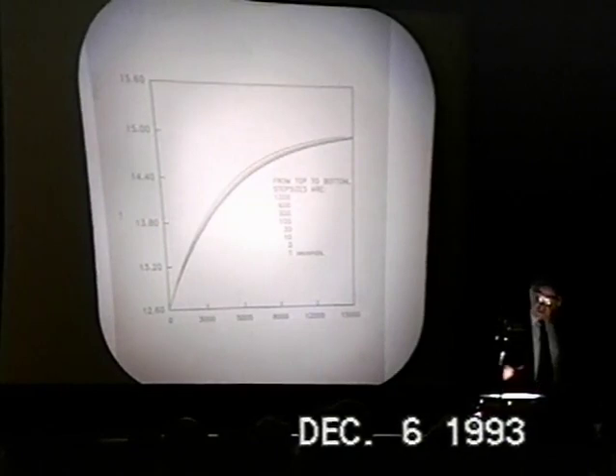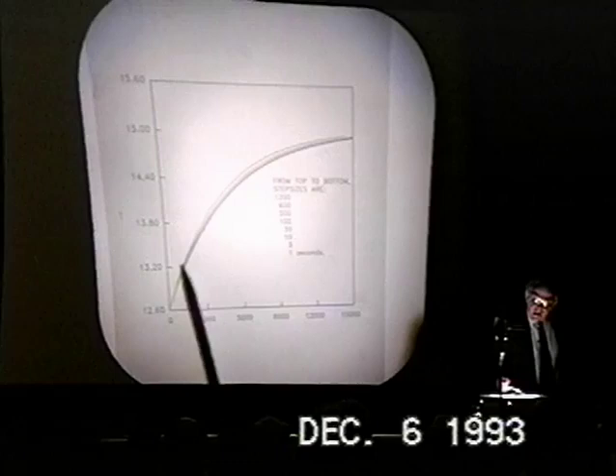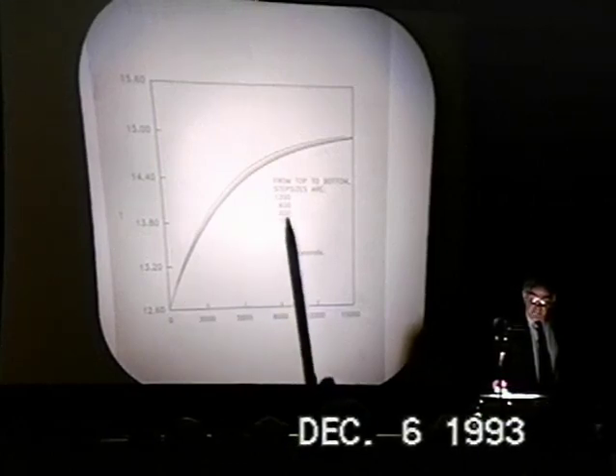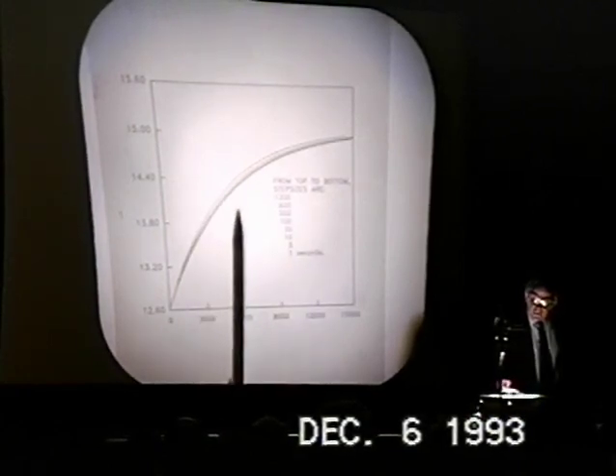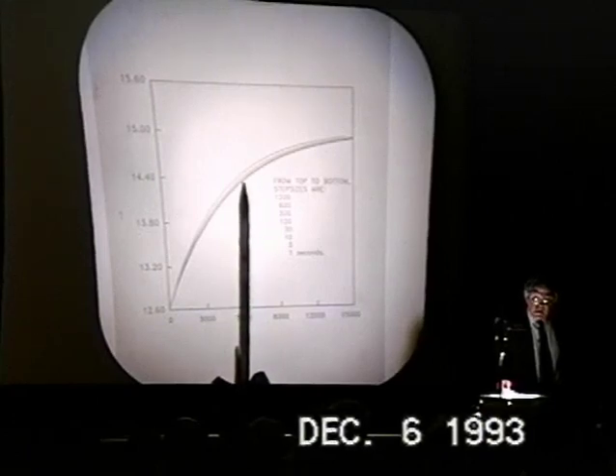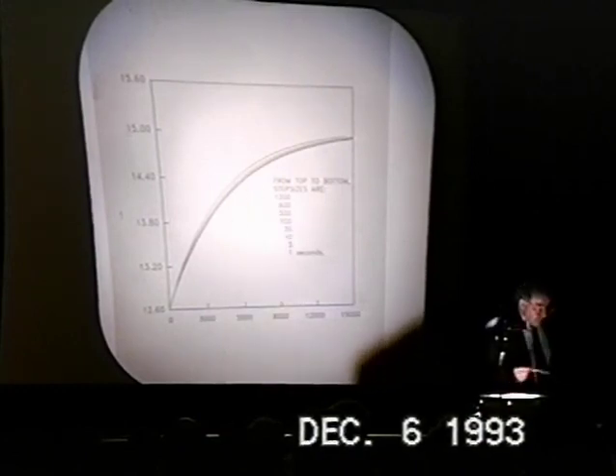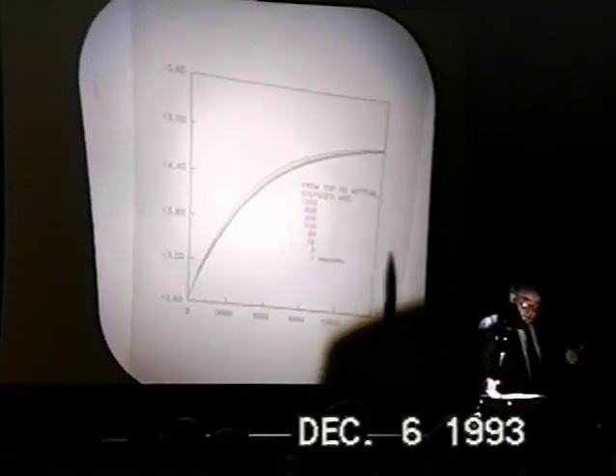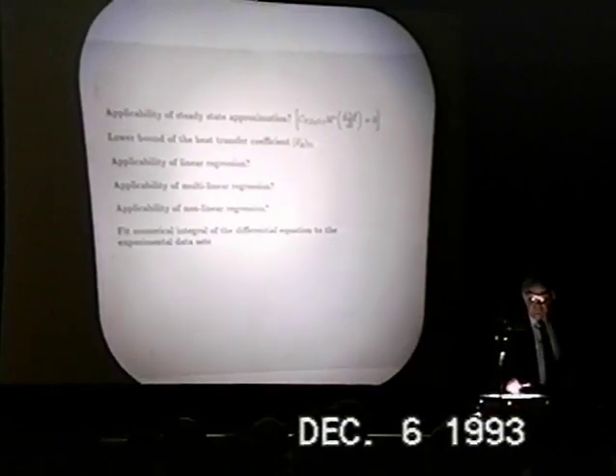Let me just explain to you very briefly why we took that particular approach. The reason is that with the particular timing sense which we used, we found that our main experiments are with about a 300-second time interval, that we push into the region where our interpretation would be affected by a Shannon limit, that it's not a sufficiently fine mesh, in fact, to treat the experimental data directly. So it makes sense to take a somewhat roundabout route to this and say, okay, well, I'm not limited by the Shannon limit. If I integrate the differential equation, that gives me just the temperature as a function of time, and then we can fit the determined numerical temperature as a function of time with the differential equation.